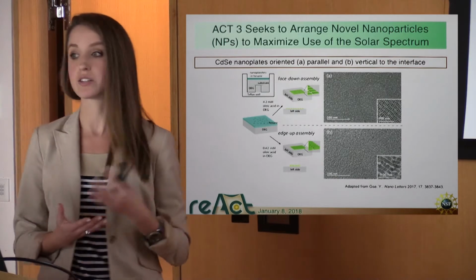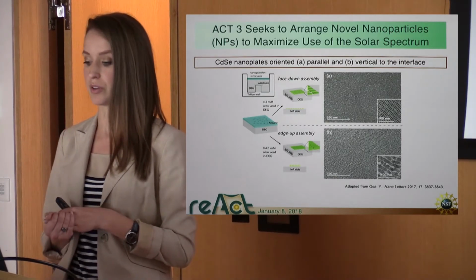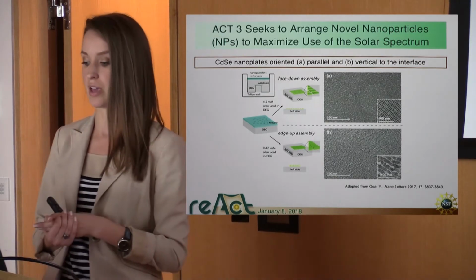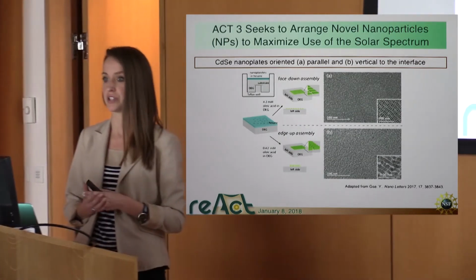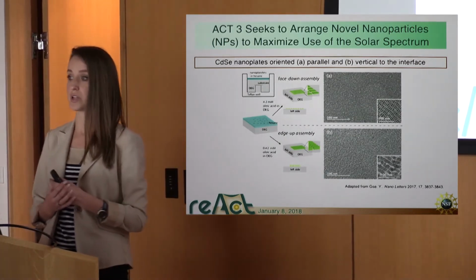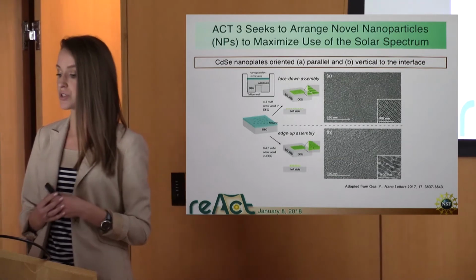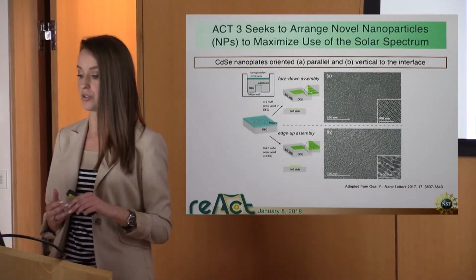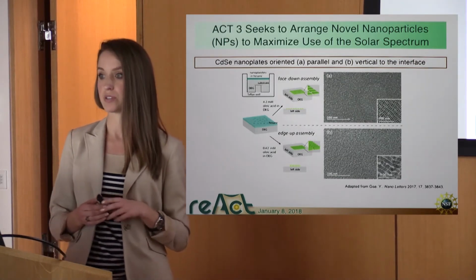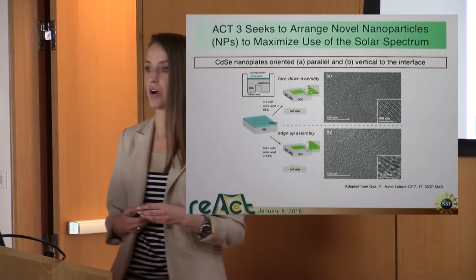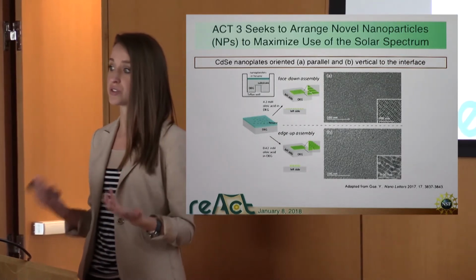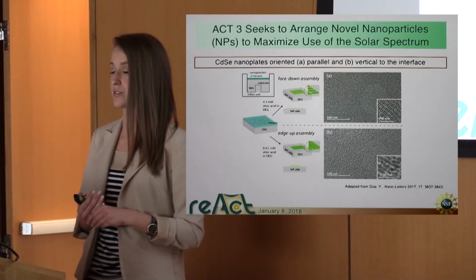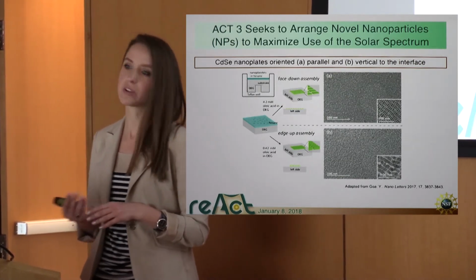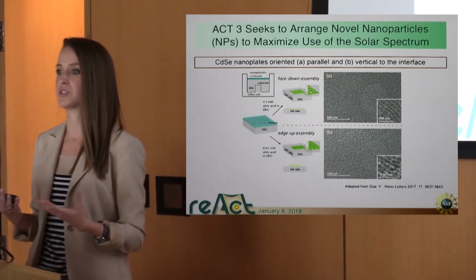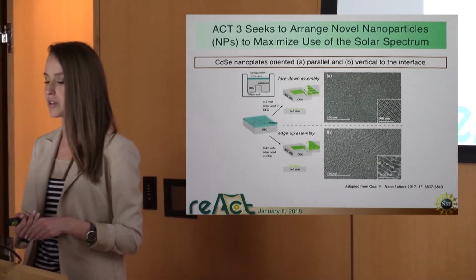So optical anisotropic or non-spherical nanoparticles, such as cadmium selenide in this case, can be assembled into different orientations on a liquid-air interface to elucidate the effect of nanoparticle orientation on properties. However, when we want to start thinking about applying this to a surface for a tent, as is the aim for REACT, we want to start thinking about putting these into some sort of coating technology,